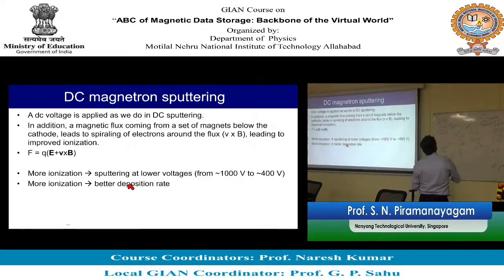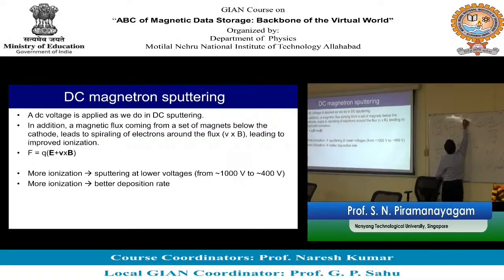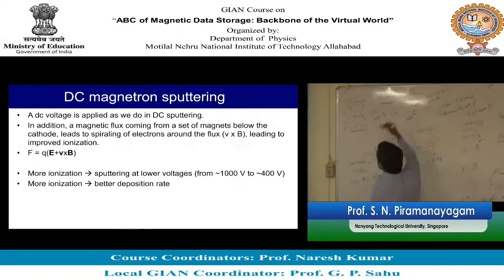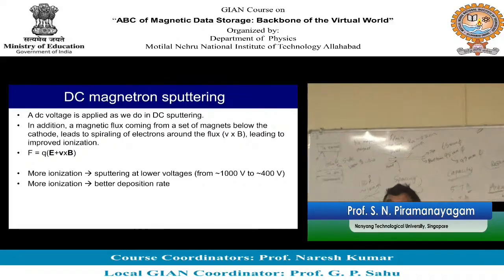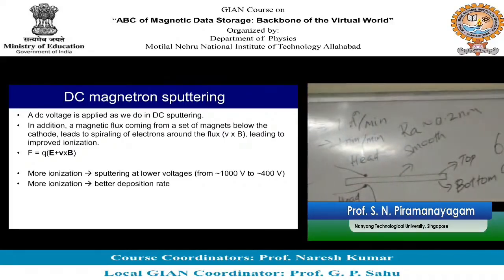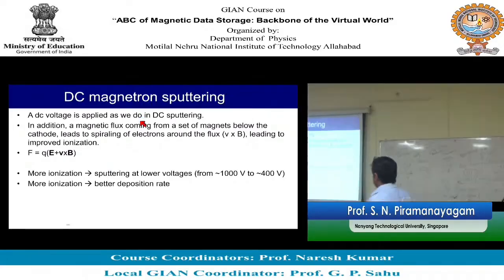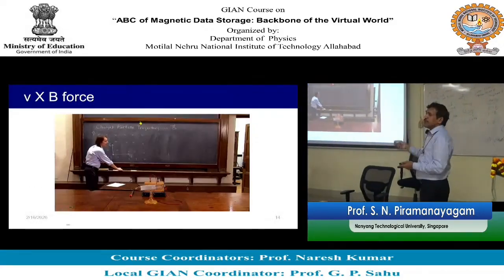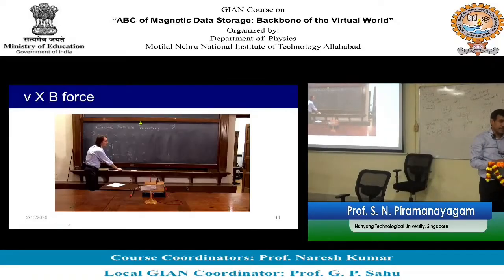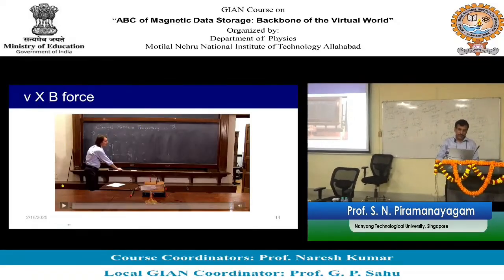Let's say with no magnet you deposit 1 angstrom per minute. With a magnet, you may be able to deposit 1 nanometer per minute or much larger. So the deposition rate can be increased by adding magnets below. This is called DC magnetron sputtering, and it is based on the Lorentz force I described before. The Lorentz force is the V cross B force.